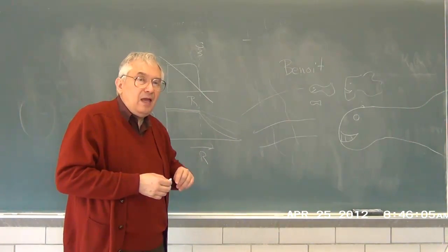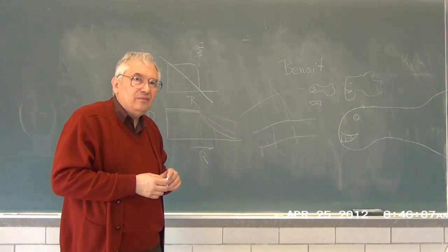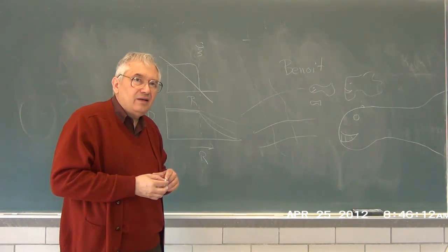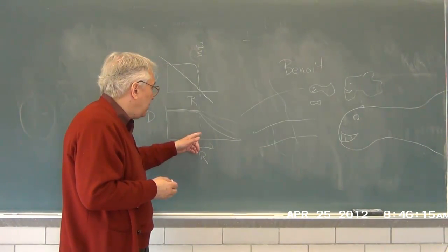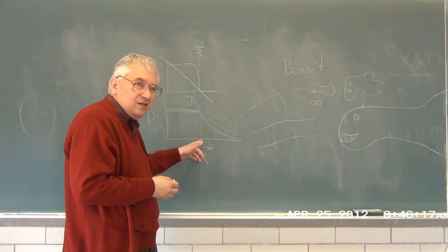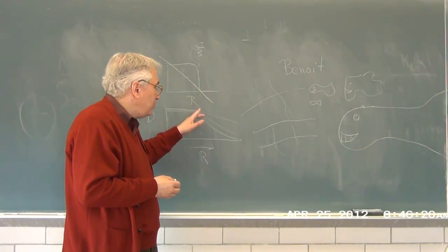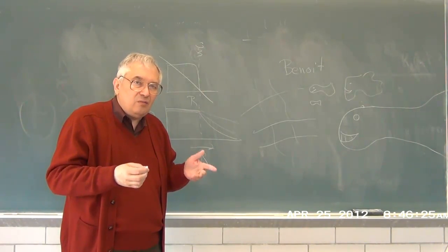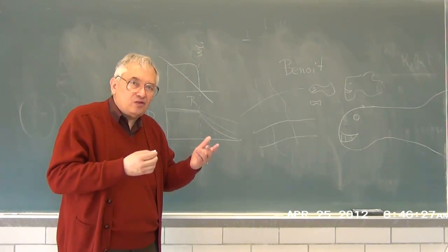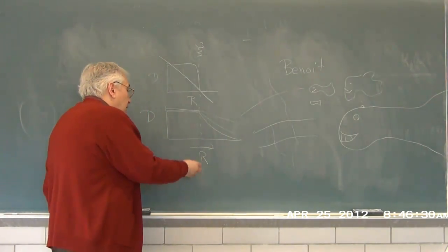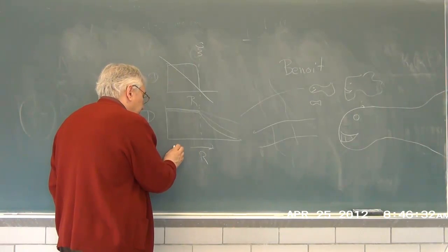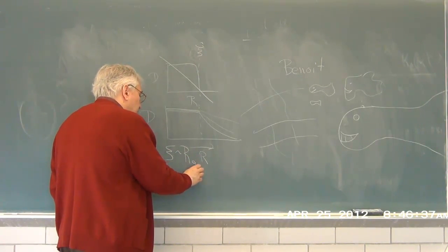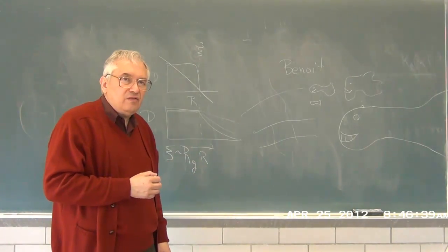Question? And this critical concentration that's there, it's not dependent on the probe size at all, is it? Oh, this is a critical probe size. Probe size, okay. Yes. Not concentration. Yes, and you see the probe size in the concentration dependence of some of the spectral parameters, which are different for small and large probes. And the critical probe size is approximately, or maybe twice, Rg, the radius of the polymer.